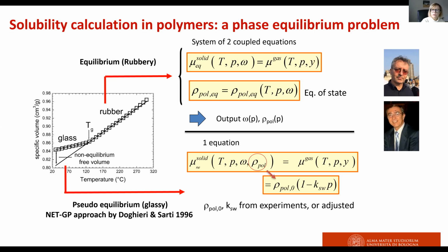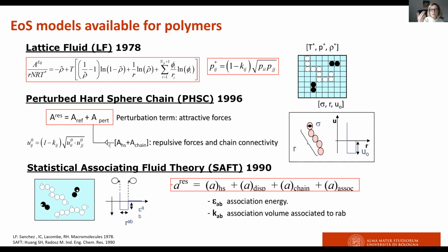You can rely on different equations of state, and you can apply this same framework, this same approach, using different available equations of state. The most suitable to the case of polymers are the lattice fluid one, the perturbed hard sphere chain, and all the equations of state based on the statistical associating fluid theory. They, of course, use a different representation of the substances. One uses the lattice, the other ones use a chain of spheres.